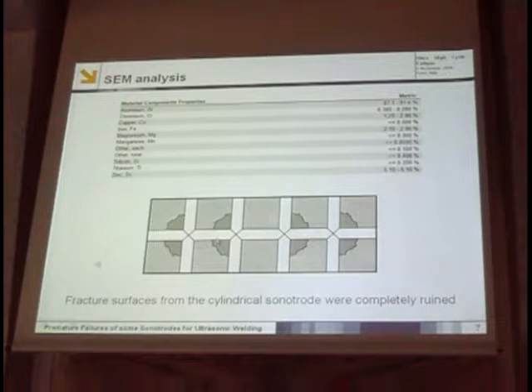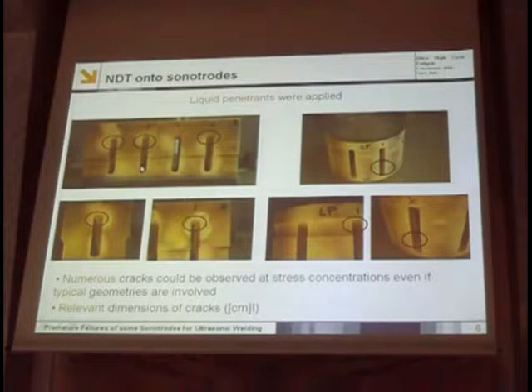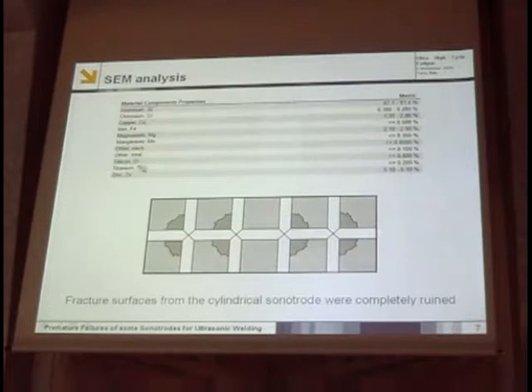Unfortunately, after the analysis, for the circular sonotrode we saw that the fracture surfaces were ruined and no relevant results could be obtained from that one. So we focused only on the prismatic one in this case. Another interesting thing that is not possible to show in this schematic is that the cracks were on both ends, so upper and lower in the sonotrode. So the schematic works for both the upper and the lower stress concentrations.